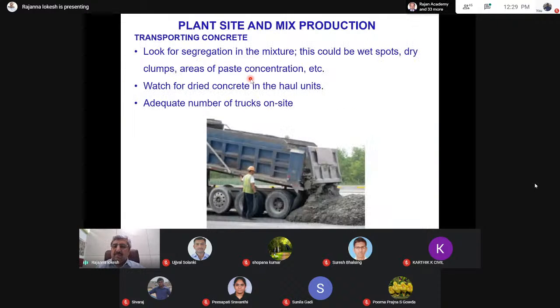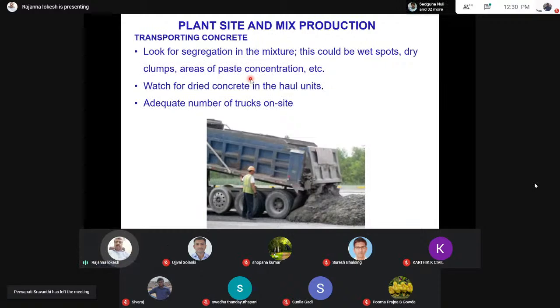So this is the placing. Since we are going with a slump requirement of 35 mm, it is difficult for us to bring in a transit mixer and pour the concrete on top at the working site. So it is always better to bring the concrete in dumpers or tippers and unload it.